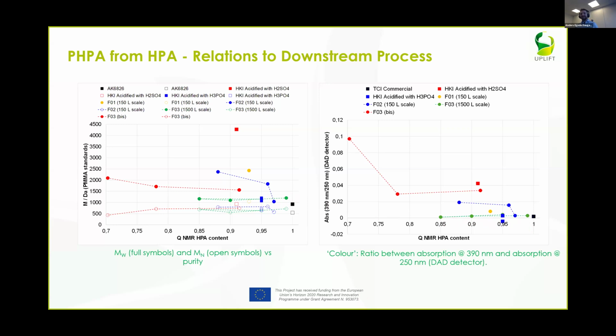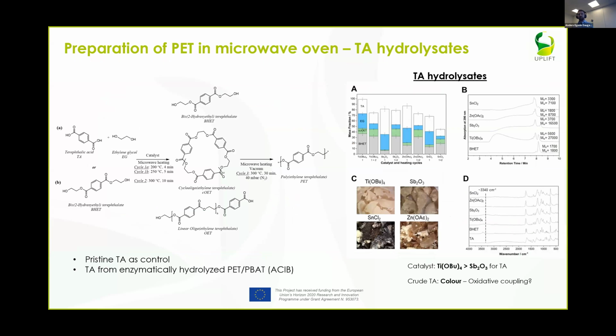So there is room to use the products at a lower purity than what would otherwise be the case. And this we have done across the different range of monomers that have been achieved or received in work package 4. So in addition to the HPA monomers, we have also received a range of terephthalic acid hydrolysates. These have primarily been produced through acid or enzymatic processes. These can then be mixtures of terephthalic acid and salts. It can also be other residues from buffers and other things that are in these systems. And what we were trying to do here was to co-polymerize these into intermediates that we could then purify, again considering the possibility to use a less pure starting material.